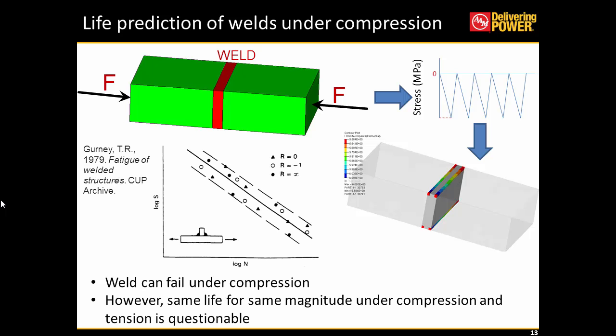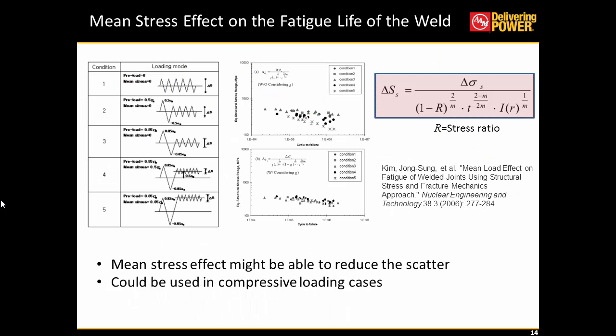There are multiple tests which have shown that weld can fail under compression, but the question still remains whether the same magnitude of compression or tension can cause the same life, because very often in our industry what we observe is that's not the case. When we predict, we are severely under predicting the results. So there is one suggestion, one way which we might be able to look into, that is to consider the effect of mean stress.